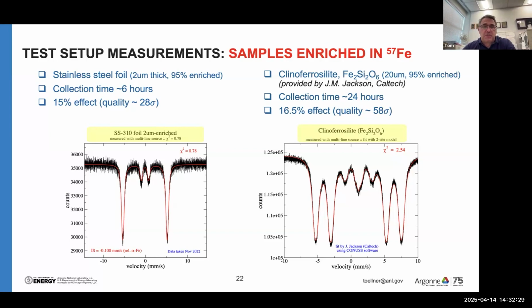Percent effect you see is 15%. Percent effect, for those that don't know, is just the ratio of the absorption dip to the baseline. So 5,000 divided by 35,000, that's where the 15% comes from. The quality refers to the magnitude of the dip relative to the RMS of the baseline, the RMS being the sigma. Typically, you want a quality of about 50 sigma for data or better. Obviously, more is always better, but given synchrotron time constraints, one has to make some compromises generally. So one would probably want to collect this longer. Also, the quality goes as a square root of time. So to double the quality would take 4 times the data collection time, just FYI.